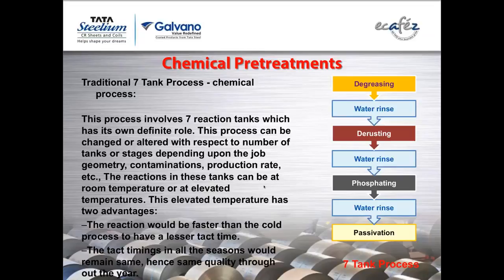Then there may be a few oils which we use. These oils can be hydrocarbon oils or petroleum oils. They will not react fully with alkalis. So we have to add some amount of surface active agents or surfactants, which will emulsify these oils and remove them. Now, if you have a very complex job, you have smaller takt times, you can always go for 2 degreasing stages. The first one is called pre-degreasing, or also knock-off degreasing or KOD. Then the second stage comes as water rinse.